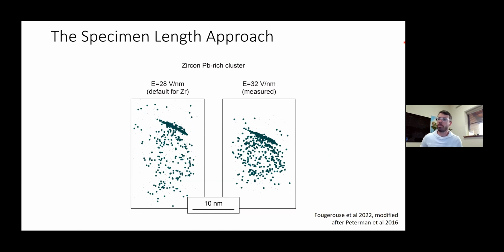So we had some good results, and this is an example here of a lead cluster in zircon. If we use the default value from zirconium, which is an electric field of 28 volts per nanometer, we see some distortion and probably an elongated cluster in the Z direction. If we use the parameters we actually measured, we see the cluster is round and probably closer to what we expect.